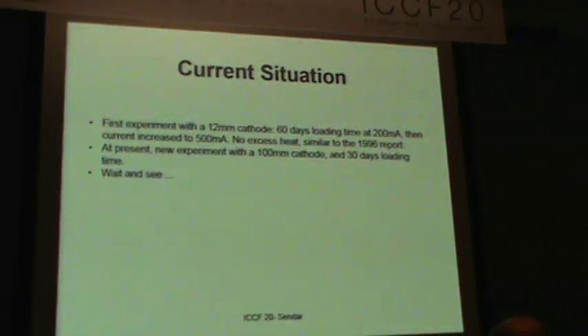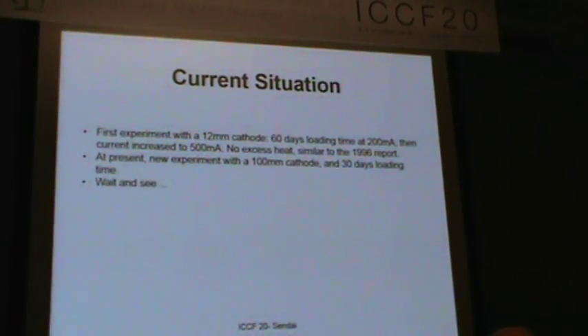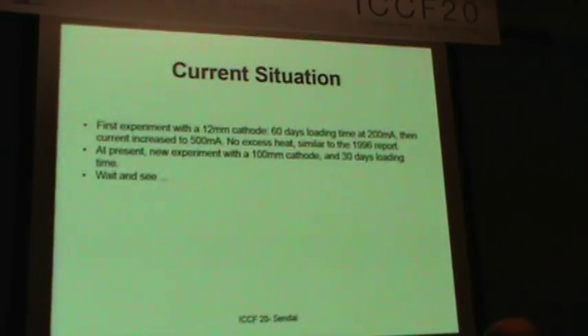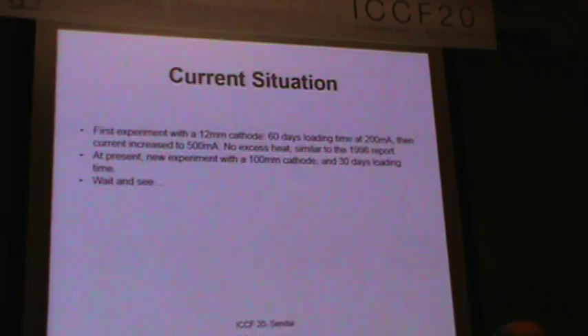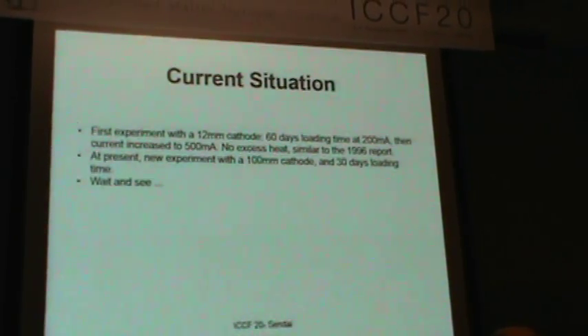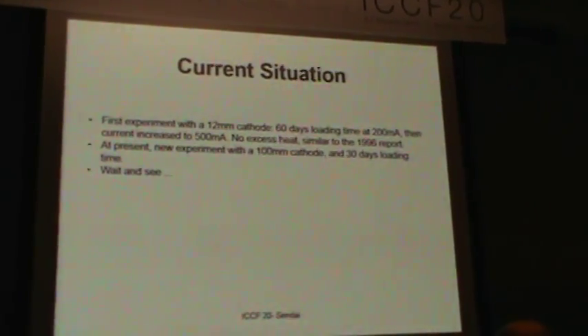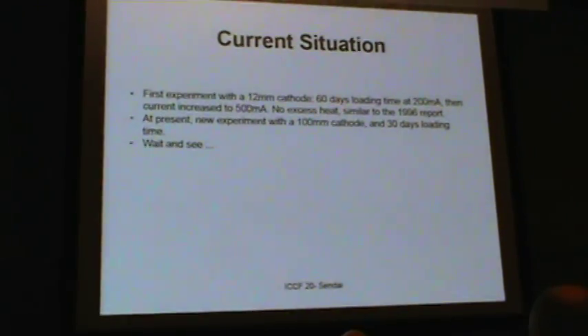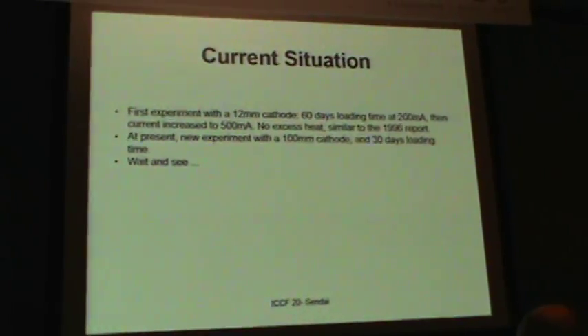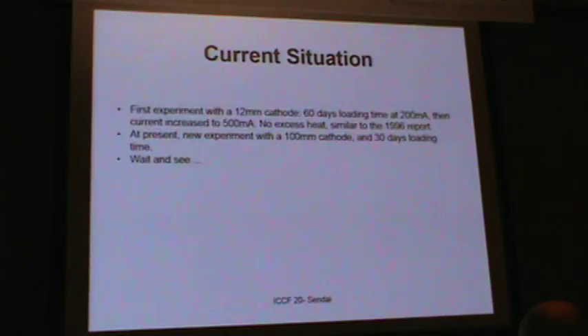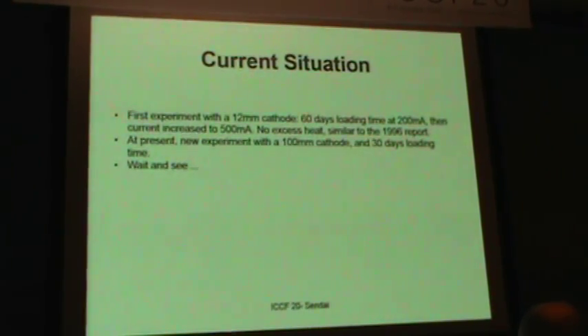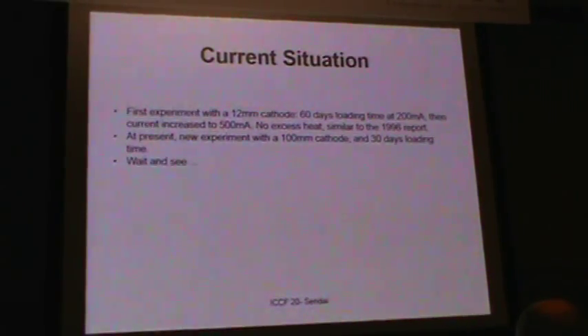First experiment I've done with a 12 millimeter cathode for 60 days of loading at 200 milliamps. And then I increased the power to 500 milliamps, but I didn't see any excess. But this is exactly similar to what happened in 1996. There was no excess. So at the present I'm running a 100 millimeter cathode, and we are already waiting 30 days. So it's working by itself at home now.